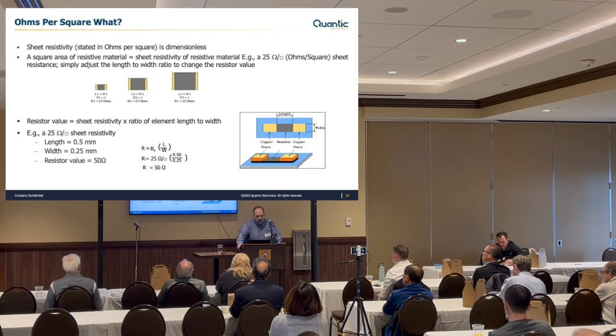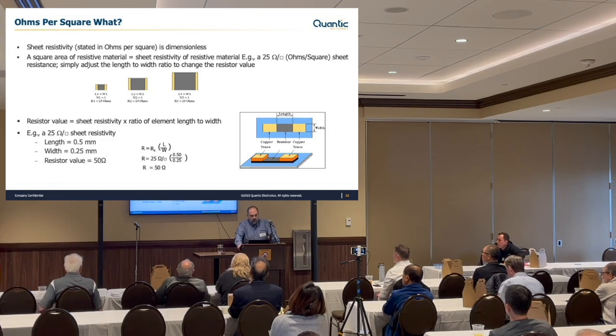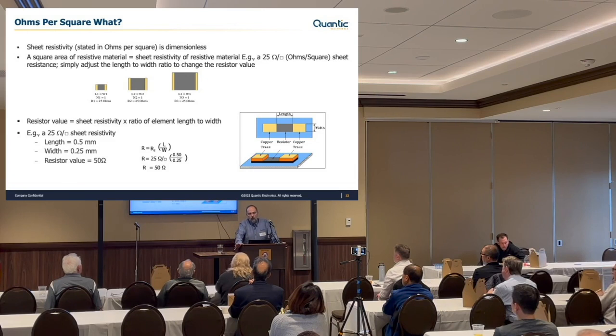So the whole concept of ohms per square, what is it? It turns out that in order to get the resistance value that you want, it's a geometry factor. So when we say ohms per square, if you look at the 3 different sizes, they're all 25 ohms because they're a perfect square. They're a 1 by 1. So whether it's 1 millimeter by 1 millimeter or 1 meter by 1 meter, it's still a 25 ohm resistor because of the way that this works. The difference in the sizes, though, is how much power you can put to it. So the bigger the resistor, the more power it can take, and also better heat dissipation.